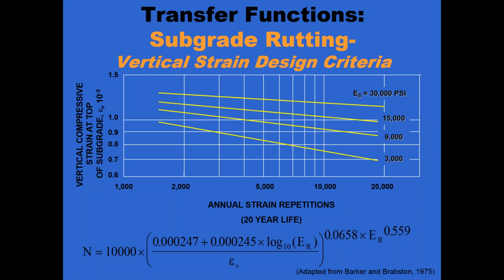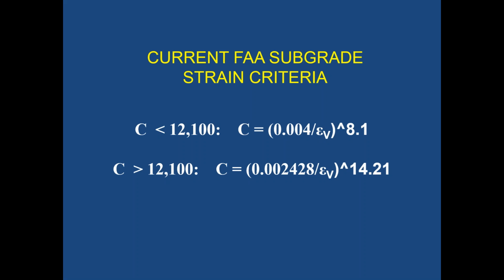This is the original FAA relationship developed by the folks at Waterways Experiment Station in 1975, where they were looking at strain, modulus of the subgrade, and what we would have for a calculated strain. So this gives you the predicted fatigue life for a range of subgrades. But once again, it gets back to the idea of resilient strain, which is in many cases probably not working very well for us.